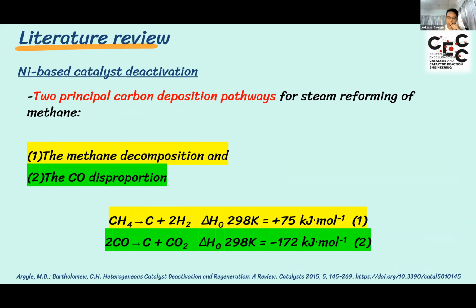Carbon deposition on the catalyst surface causes catalyst deactivation, and there are two principal carbon deposition pathways for steam reforming of methane. First, methane decomposition, which is shown in Reaction 1. Methane decomposes into carbon atoms and hydrogen gas. And the second is CO disproportionation, where CO disproportionates into carbon and carbon dioxide. And the carbon atoms can cause carbon deposition on the catalyst surface.